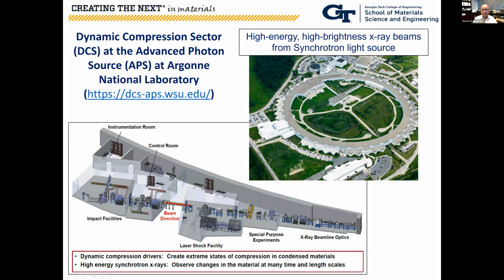This is the synchrotron source at the Advanced Photon Source at Argonne National Laboratory, where there are high energy, high brightness X-ray beams necessary for doing X-ray phase contrast imaging. There is the dynamic compression sector, which has a range of gas guns, a laser flyer setup, as well as explosive chambers, and that's the setup we use for our experiments.